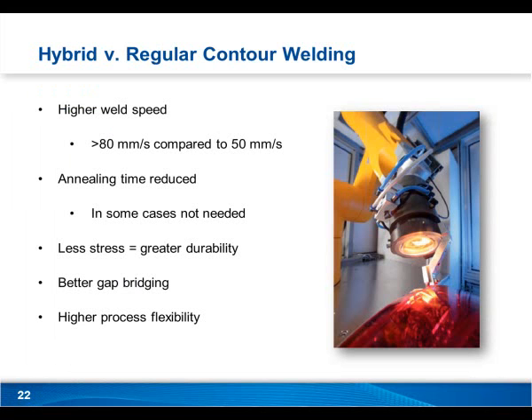All right, so jumping back into where we were, hybrid versus regular contour welding. Like I mentioned, you can get higher travel speeds. So 80 millimeters per second compared to 50 millimeters per second, because we're essentially preheating the plastic. The higher laser power can be realized because the upper layer is being heated by this halogen lamp.